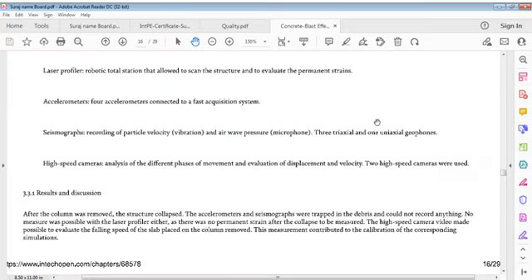Results and discussion. After the column was removed, the structure collapsed. Accelerometers and seismographs were trapped in debris and could not record anything. No measure was possible with the laser profiler either, as there was no permanent strain after collapse to be measured. The high-speed camera video made it possible to evaluate the falling speed of the slab placed on the removed column. This measurement contributed to calibration of the corresponding simulation.